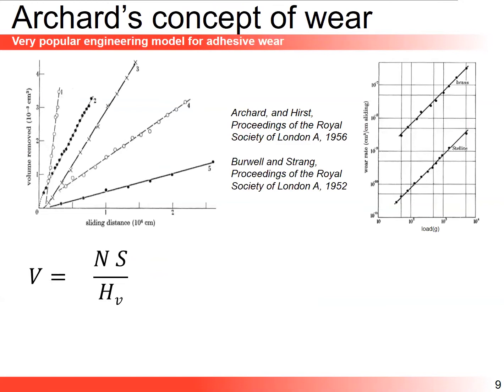Okay, so here I'm turning to the best known and most used equation for wear, out of those 300 equations. It's called Archard's wear law, very popular because it's very simple. This equation tells you that the production of wear volume V is linearly proportional to the applied load, linearly proportional to the sliding distance, which you can relate to the life expectancy of a component in an industrial machine, and inversely proportional to the hardness of the material. And you have here data showing indeed this linear proportionality.